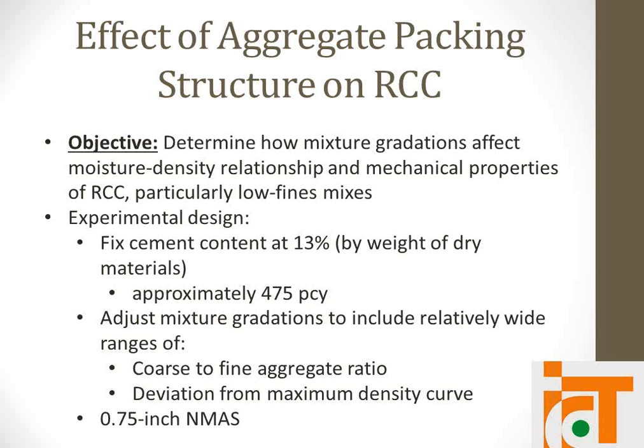So we're going to look at moisture density relationship and mechanical properties of RCC to see how gradation has an effect on those. So we fixed the cement content at about 475 pounds per cubic yard, a little bit less than IDOT's minimum, which is, I think, 520. And this is shown to give us good results, and we thought 520 was a little overshooting it.